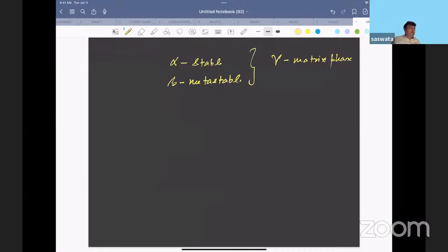Do you have the free energy? Say, for example, you know the compositions. In Thermo-Calc, there is a way to plot all these free energies as a function of composition. You can draw like a quasi-binary section. You don't have to do a ternary surface, but you can do it along certain carbon compositions.